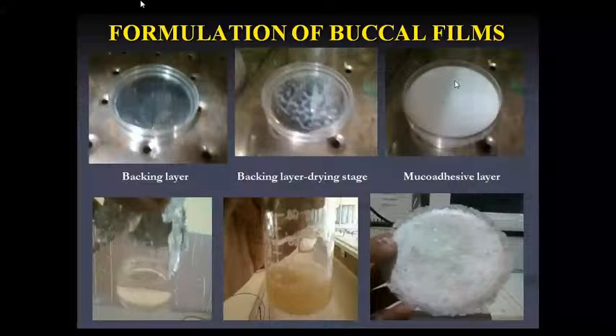After that, look at this one. This is the beaker containing the polymer, the mucoadhesive polymer, maybe SCMC or HPMC, whatever. That polymer is dissolved in water. In that, propylene glycol must be added. Propylene glycol acts as a plasticizer of the film. And you also need to add the required amount of your drug, and mix it thoroughly to ensure there are no air bubbles inside it.